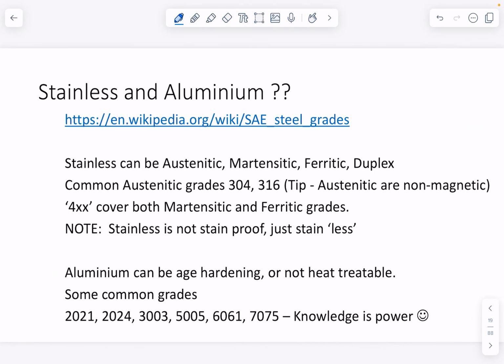So that was just touching on carbon steel, mild steel. There is also stainless steel and aluminium. Wikipedia's got everything these days, and has a pile of information there. If we look at stainless steel, we can get austenitic, martensitic, ferritic, and duplex, and I think there's one other grade as well. If we look at austenitic, 304 and 316, surgical stainless is basically 316, or an 18/8 alloy, 18% chromium, 8% nickel. And the tip is if you walk around with a magnet, austenitic stainless steels are not magnetic. That's sort of how you tell them apart.